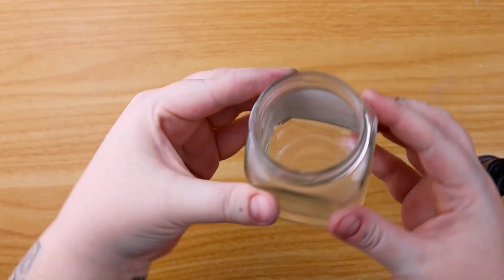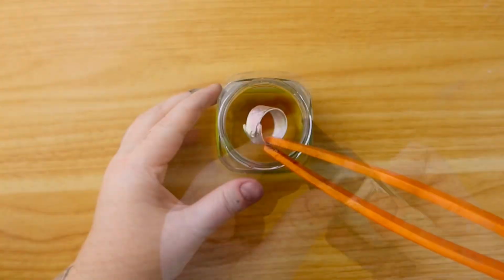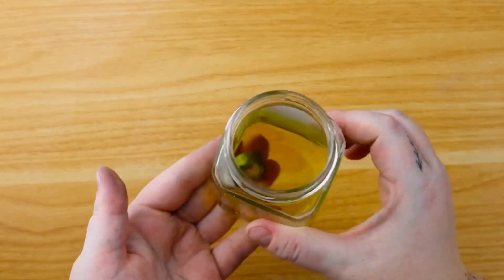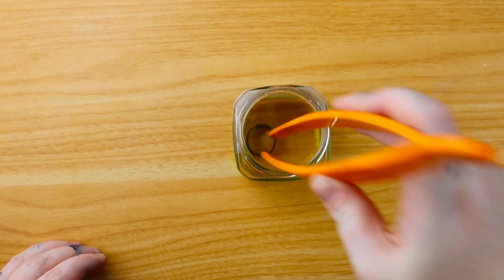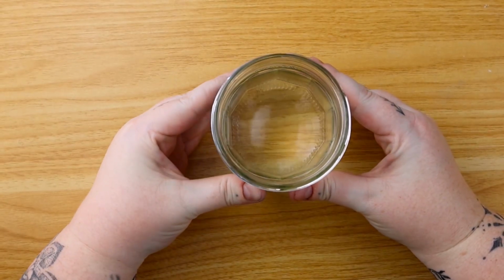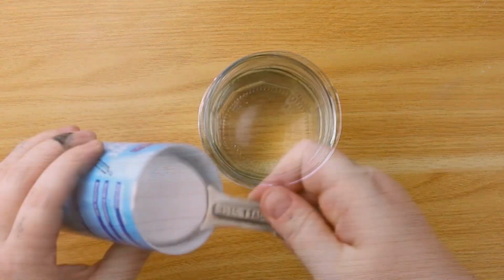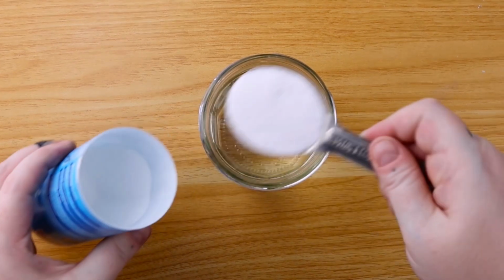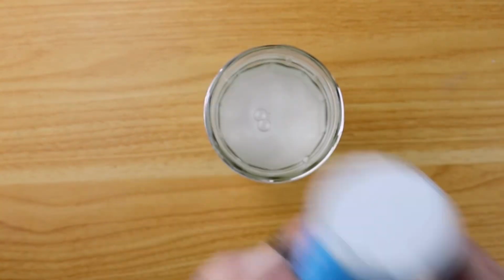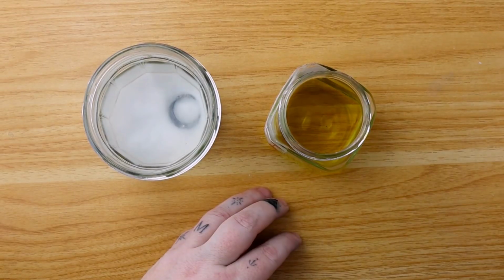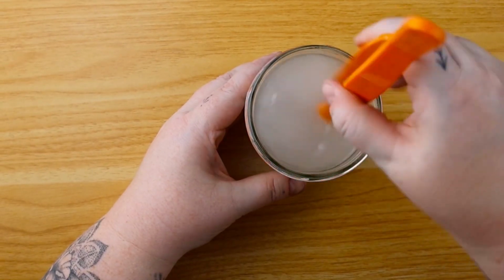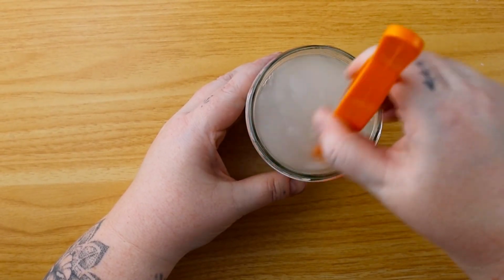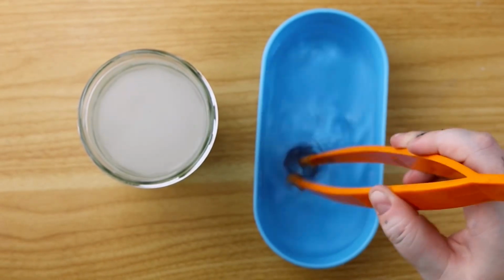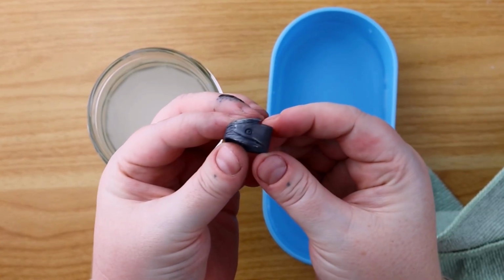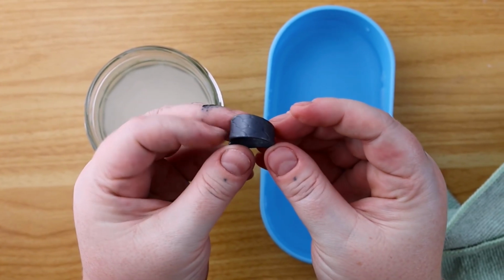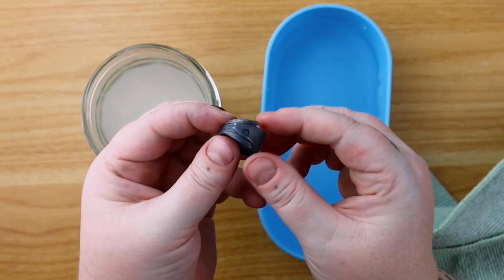Here I'm going to add a few drops of liver of sulfur into some warm water, dipping my ring in and out to let it develop to the darkest tone. Once we have patinated our ring, we now need to neutralize it. Here I'm adding 1 tablespoon of bicarbonate of soda into a cup of warm water. I'm going to allow my ring to sit in there for 1 to 3 minutes. We do this so the process of oxidizing stops. Once I'm happy, I'm going to give it a little wash with some soap and water. And here you can see it is completely oxidized to the darkest colour.